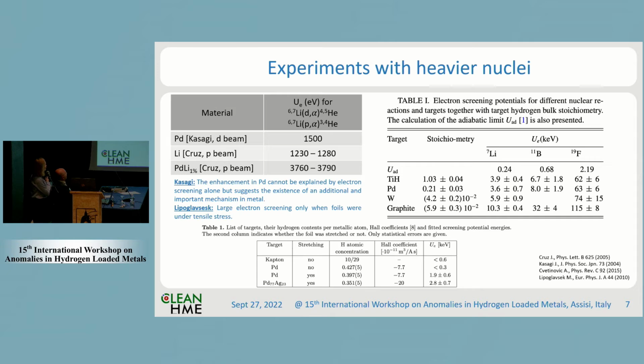Then we had a lithium target, and again, this was the proton beam reaction, so this is this one. And the value, depending on whether this was lithium-6 or lithium-7, was different. And they also did the same kind of reaction with the proton beam on a palladium-lithium alloy. There was only a small amount of lithium in palladium, and the values are even higher than that.